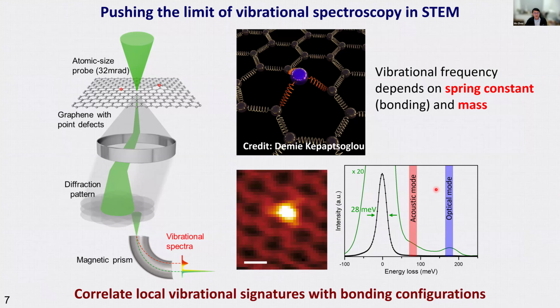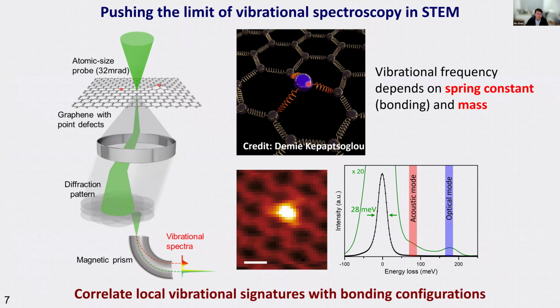So in order to see this, we actually first need to go back to the very simple model, a harmonic oscillator. We can use this model to describe the vibrational frequency. So the frequency will depend on the spring constant, and at the atomic scale, this is the chemical bonding strength, and also depends on the weight of the ball, which is the atomic mass here. So in order to decouple these two contributions, we need to have a very stable microscope and very high signal to noise ratio in the spectroscopy data. So we can look at the spectroscopy data from each individual atom around this point defect.